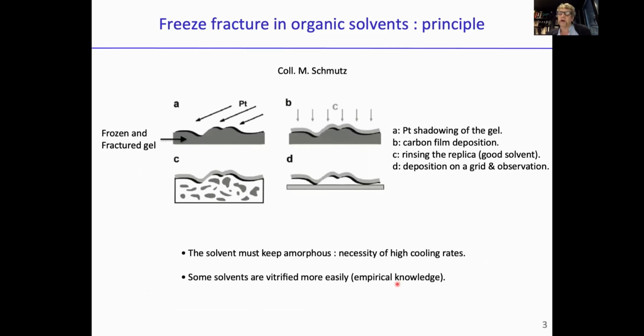So this is the principle, for those of you who don't know what freeze fracture is. The principle of freeze fracture consists of freezing the sample. We make a deep freeze of the gel at a very high rate so that the solvent stays amorphous. And then the gel is cleaved, and you see that the cleavage is not straight, it's not a plane, it goes along the least resistance area where the self-assembled objects are.